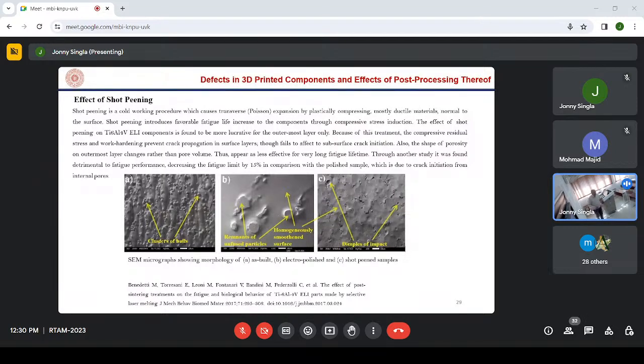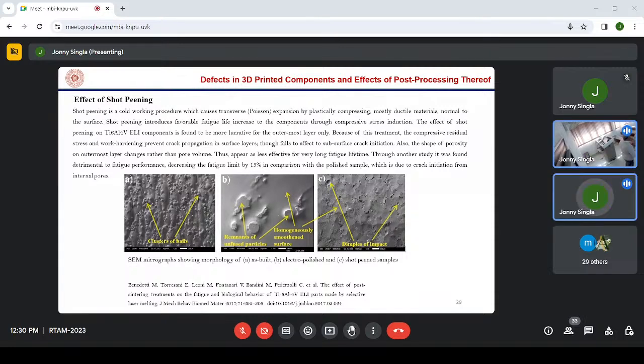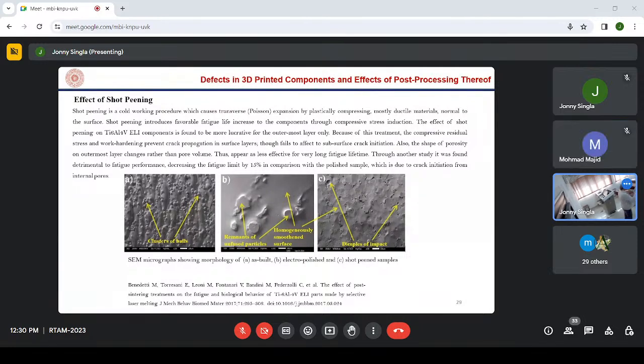If your material has compressive stresses, residual stresses that are compressive in nature, then your material will have longer fatigue life. Fatigue performance will be high. And if the component has tensile stresses as residual stresses, then it is going to fail early. That means fatigue life will reduce. With shot peening, we are externally, deliberately introducing compressive stresses into the material. Right? And that is going to increase the fatigue life of the material.